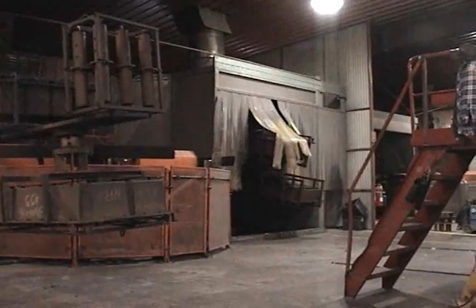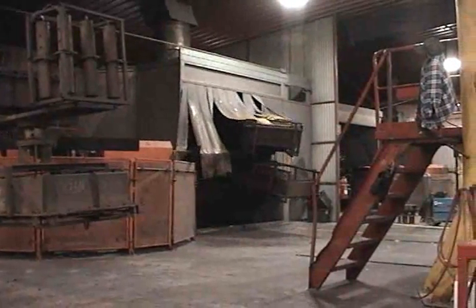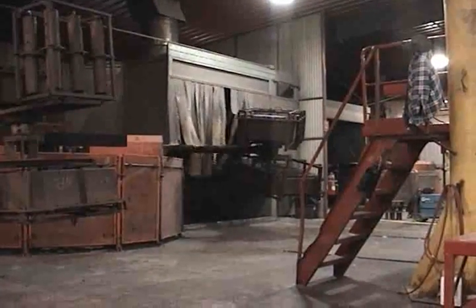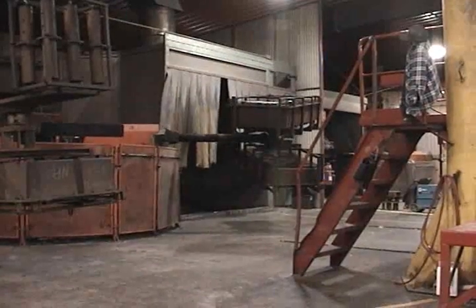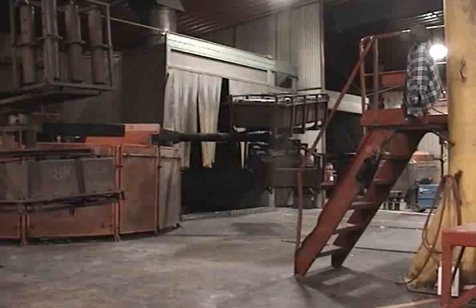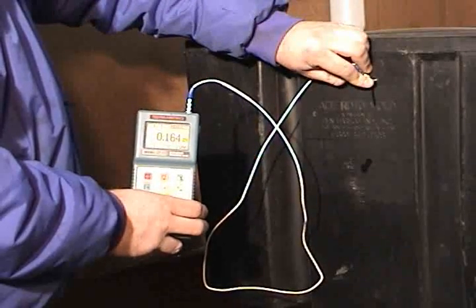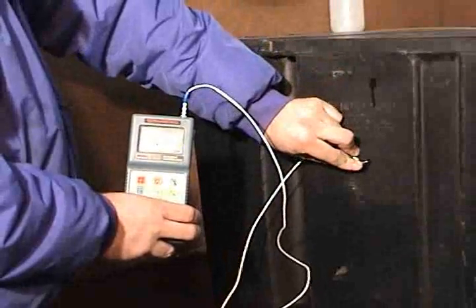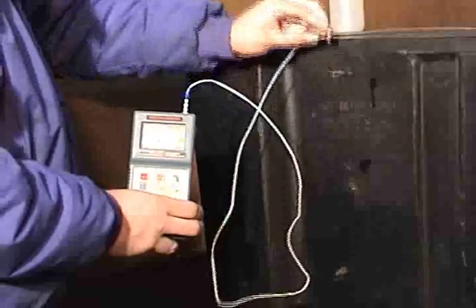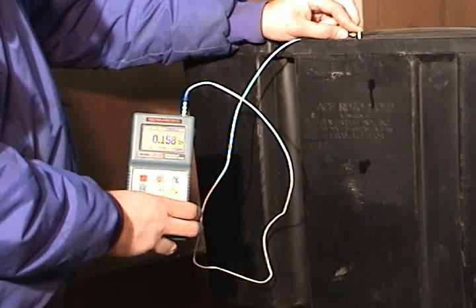The quality testing is not over once the parts are complete. What makes A-stock floats better are the quality standards and time-tested proprietary processes in place at Den Hartog Industries. This is where the cure makes a big difference. Let's talk about outer shell wall thickness and outer shell curing first. A-stock floats are sonically tested to ensure that a nominal wall thickness of 15 one-hundredths of an inch is maintained at all points in the outer wall.